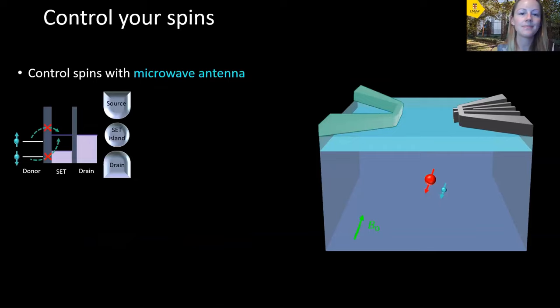So now we have our system and we know its Hamiltonian. How do we control our spins in the system? Well, we do this using a microwave antenna highlighted here in green. And this applies an oscillating magnetic field that's capable of spinning our spins around. First of all, we need to make sure that our donor electron is trapped onto the donor nuclear site by raising the Fermi level of the single electron transistor island above both the spin up and spin down energy levels of our donor qubit. And so basically the electron remains trapped on the donor and it doesn't tunnel off onto the single electron transistor during this part of the experiment.